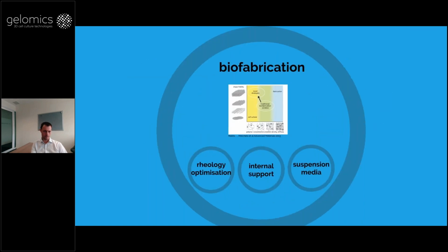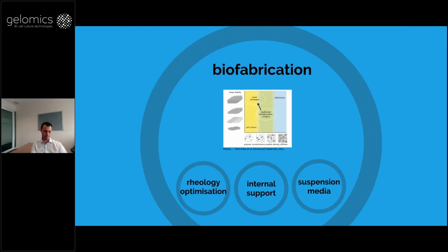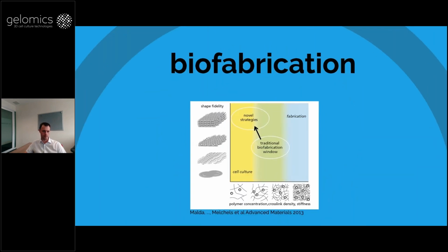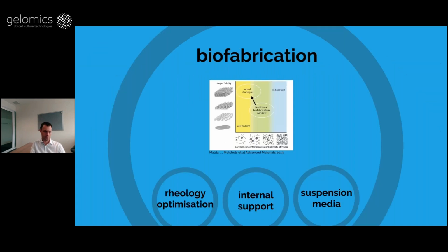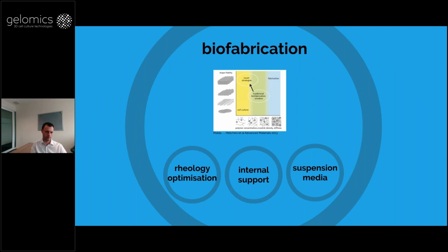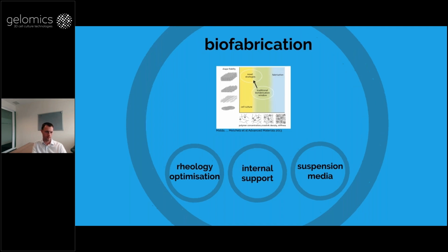Let's look at biofabrication using GelMA for fabricating constructs. We still have this dilemma when we're fabricating or printing with gels, that cells typically tend to favor soft gels, snotty, low polymer concentrations, low cross-link densities. But if you want to build a construct with a high shape fidelity, you want something stiff and a lot of polymer and not too much water. So there's always a trade-off, or you find strategies to get the best of both sides. So three different strategies we follow are to optimize rheology of the gel itself, or to use internal supports, or to print into suspension media.